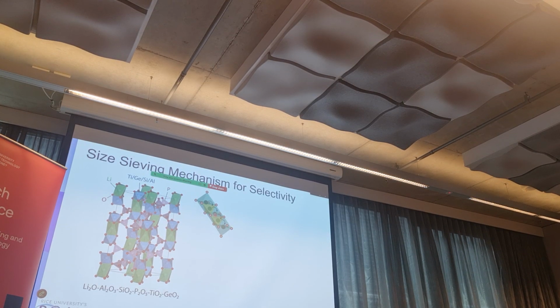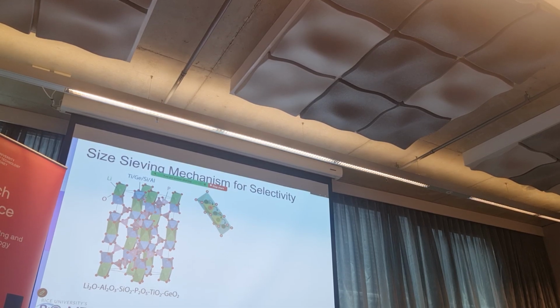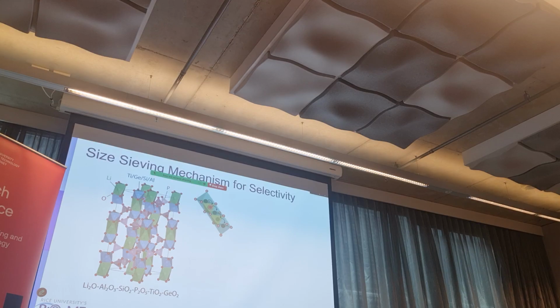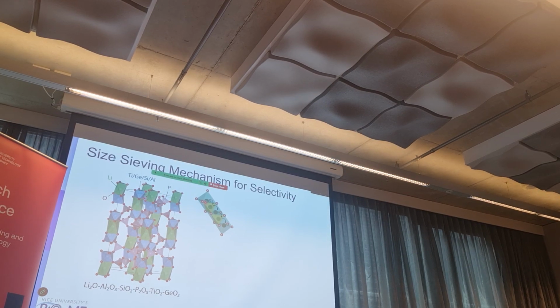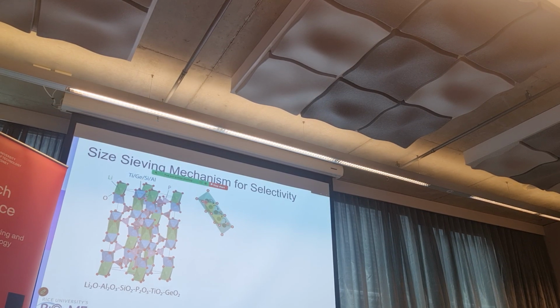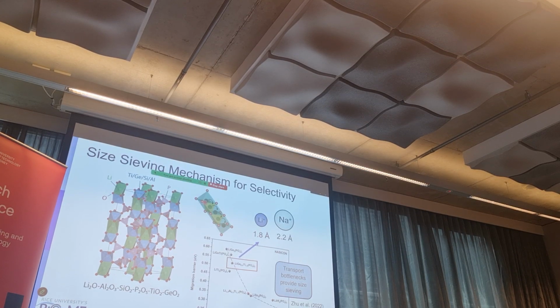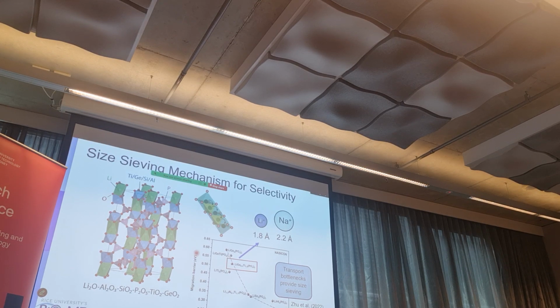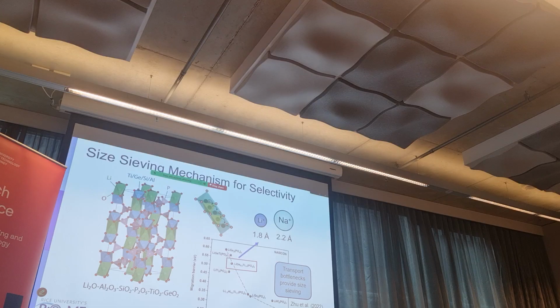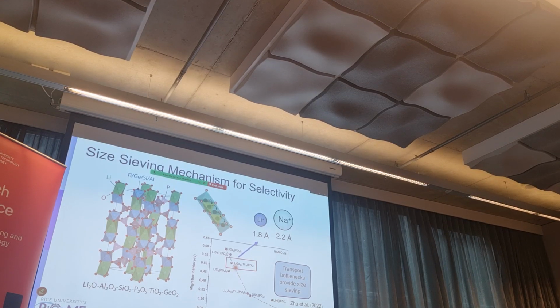Importantly, when you go from one polyhedra to another, from octahedral to tetrahedral, there is a small bottleneck you need to go through. The size of this bottleneck is very important, and this is what I'm going to show here. This shows the migration barrier, the difficulty to migrate, versus the bottleneck size between the connected polyhedra.